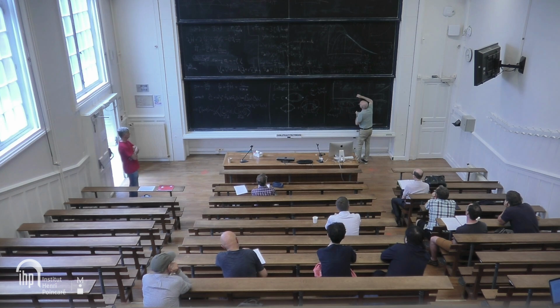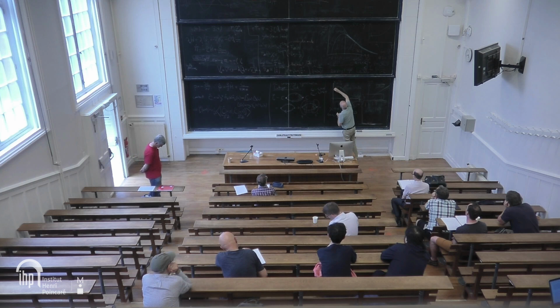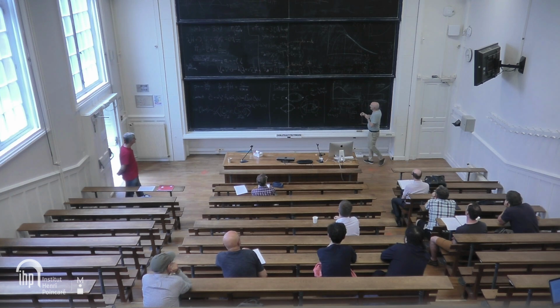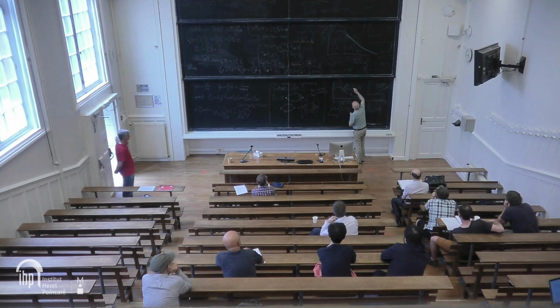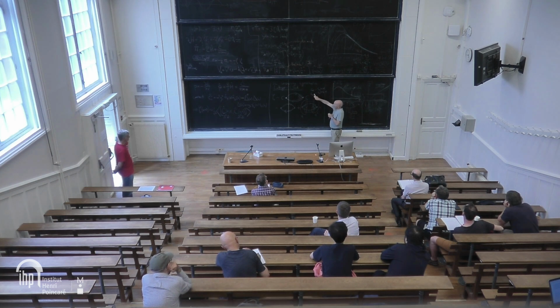So what we see is that indeed SAF grows and then goes down like that. And the onset of this thing, which of course is a crossover, you can negotiate how to define it, defines the pseudogap. So this is exactly what cluster DMFT is saying. On the other hand, the SDW structure factor is doing nothing here, and here it starts growing and overcomes this.